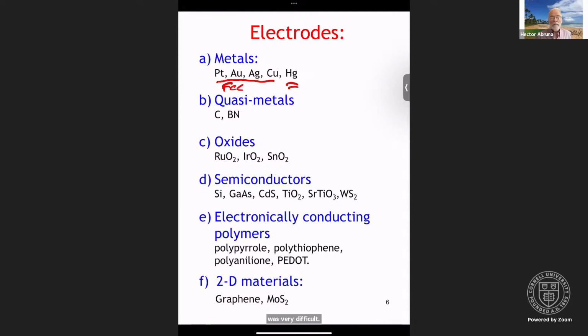Mercury was used because, let's say, 50, 60 years ago, it was very difficult to get clean metal surfaces. And mercury, because it's a liquid, if you have it in a so-called dropping mercury electrode, every 3 or 5 seconds, you have a fresh electrode. So it makes the experiments much easier, but again, considering the limitations that it poses. You can have quasi-metals, things like carbon, boron nitride, carbon in all sorts of different forms, be it graphite, be it glassy carbon, be it graphene, etc.